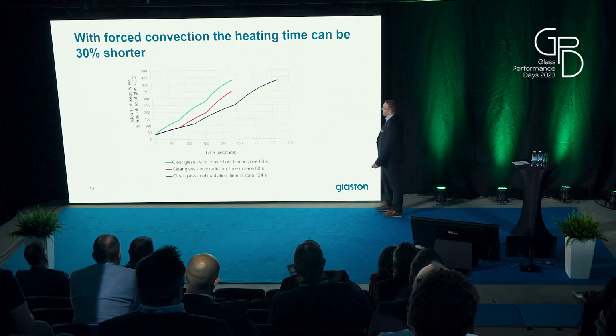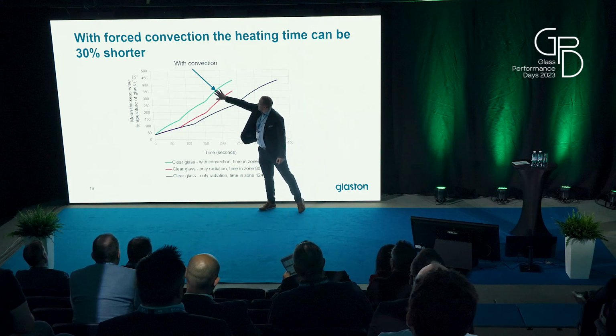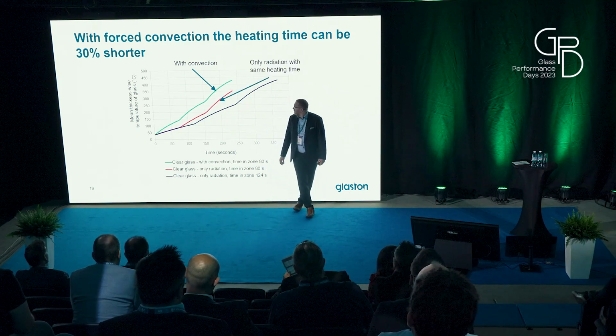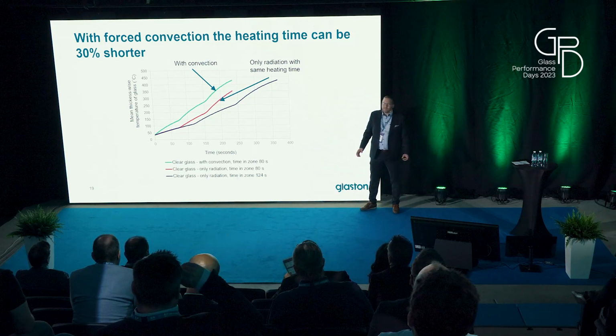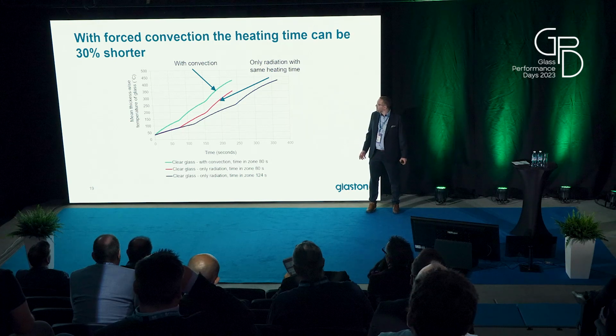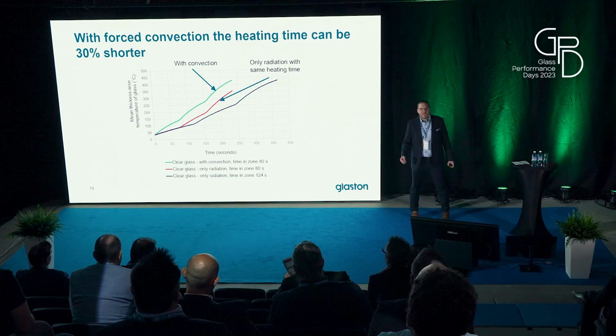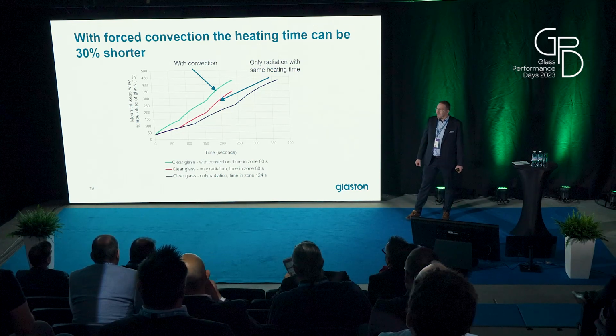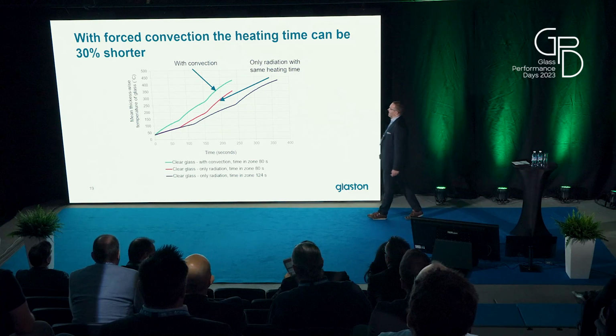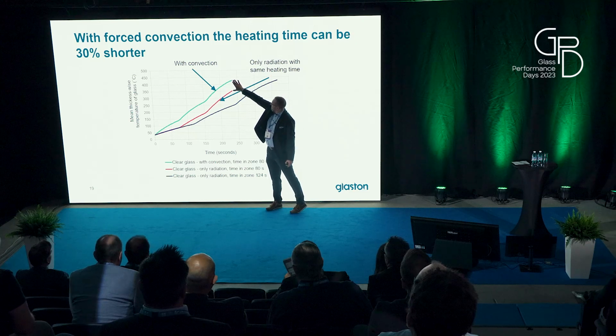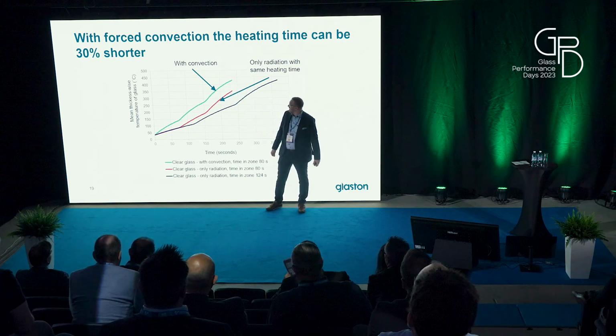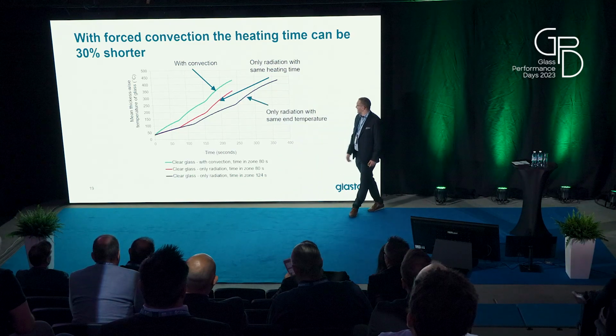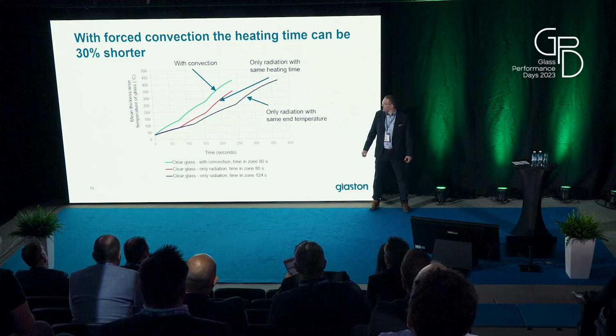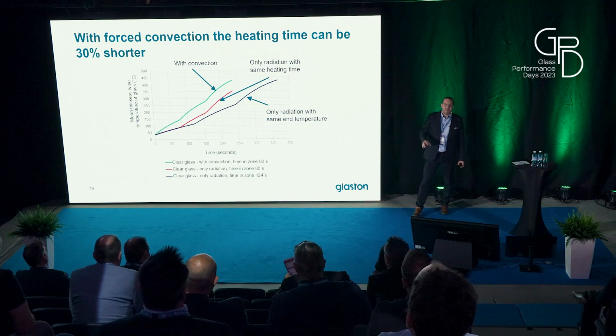So, like in these results, the green line is with convection, and the red one is with radiation, with the same heating time. We can see that with convection, we have been able to increase the heating rate, and that way we will meet the target temperature faster than with only radiation. And also, if we want to get the same end temperature, we just have to increase the heating time for radiation. So we can save some time in processing by adding this convection.